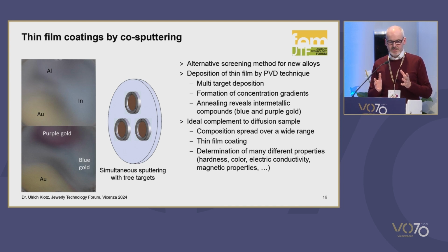But there is a difference between these two methods. With the sputtering technique, we map the area over a wide range, which makes it easy to characterize the properties. With the diffusion couple, everything is in a very narrow range, so we have to have very specific measurement techniques. So that's a benefit of the thin film coating. On the other hand, the thin films are just thin films, so they might behave differently than a bulk material. And so with the diffusion samples, we are much closer to the bulk material. So ideally, we can use a combination of these two different techniques.